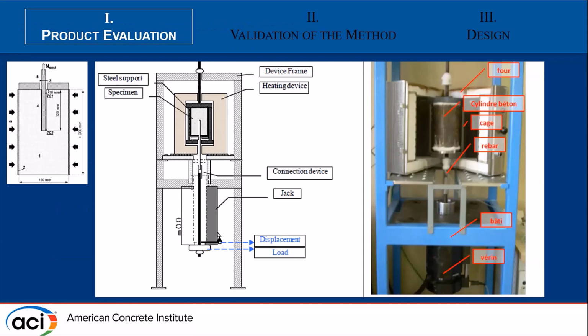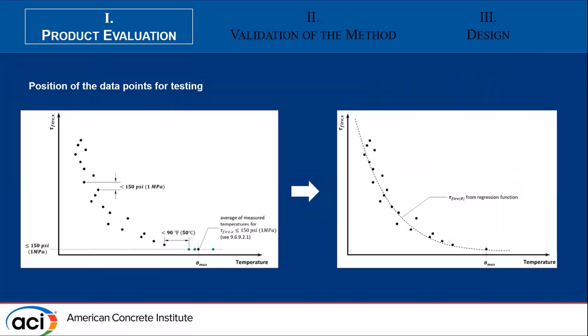So product evaluation is achieved by doing tests. These tests are done on small concrete cylinders, which are about 10 inches of height. We bond a rebar inside the cylinder, and we position two thermocouples along the bond in order to measure temperature directly along the bond line. The sample is then taken and put inside an electric oven, and the bar is connected to a hydraulic jack, which applies a constant load all throughout the heating. So we heat up the sample, and at a given temperature, failure occurs. So for a given load or stress, we can associate a given temperature. And by repeating these tests several times with different load levels, we obtain different temperatures, and we can plot the bond strength versus temperature relationship.